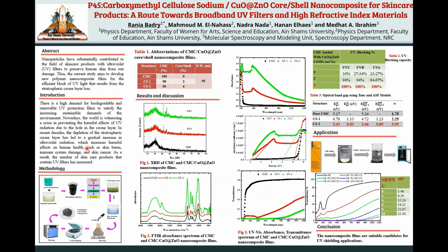Thus, we prepared the core shell nanoparticles as presented in this figure using the precipitation method, and then we added different weight percentages of the prepared core shell nanoparticles to the CMC solution using the casting method. The XRD results confirmed the amorphous nature of the prepared polymer nanocomposite due to the appearance of the broad peak at nearly 2 theta equal to 20 degrees.